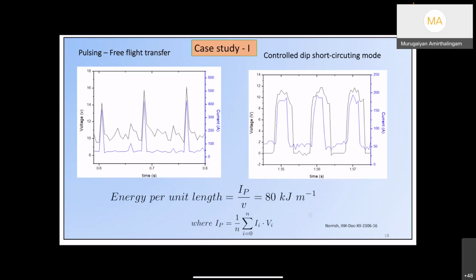In the welding case, the current voltage waveform we use is one of the important factors, because of the metal transfer, when the consumable melts and deposits. The actual temperature of the melt pool and of the droplet which is transferred is determined by the current voltage waveforms we use. In any arc welding case, we can use a constant current, or we can also use a pulsing current where one pulse of current leads to the detachment of one droplet. There are other methodologies we can use to detach the droplet from the consumable wire into the molten pool. Instead of using a free flight transfer, so what is a free flight transfer?